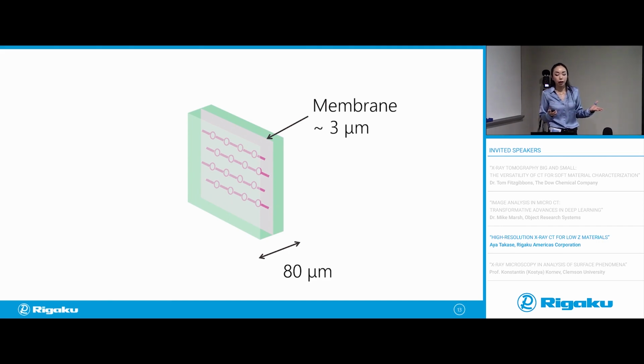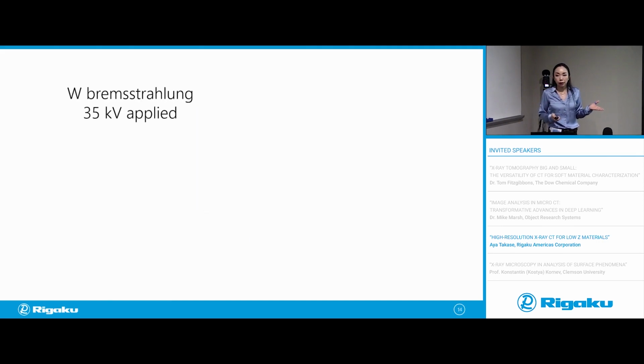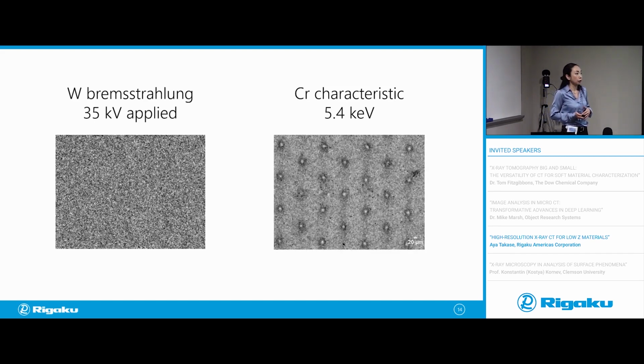of X-rays. And if you look at this sample using a tungsten target with the bremsstrahlung, or this broad spectrum, even if you lower the applied voltage to 35 kV, in the projection you really don't see anything because all X-rays are just shooting through the sample. But if you use chromium characteristic radiation at 5.4 keV, you can clearly see the pattern that's coming from the